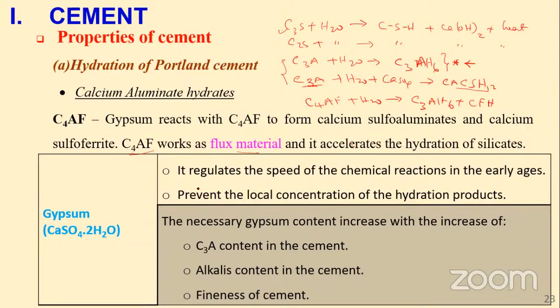Now, just to mention gypsum in detail, hydrated calcium sulfate. We have seen how it regulates the speed of the chemical reaction in the early stages and prevents local concentration of the reaction product. The amount of gypsum needed will depend on the tricalcium aluminate content in cement, because the higher the content, the more gypsum you need to control that reaction, the alkali content in cement, and the fineness of cement. Again, the finer the cement, the higher its reactivity. But if it reacts very fast, a large quantity of heat may be generated, causing flash setting. It's a balance.